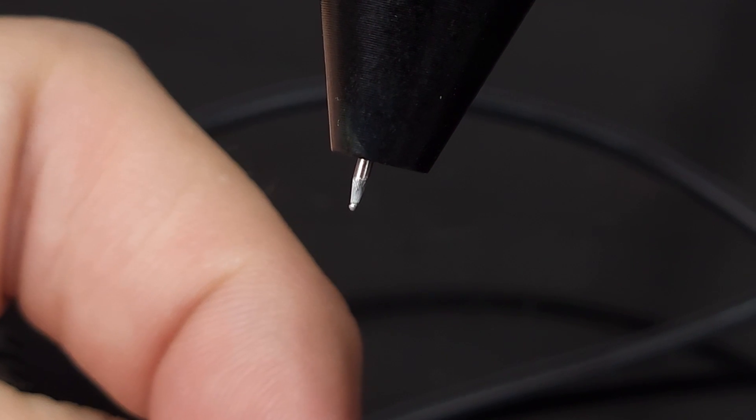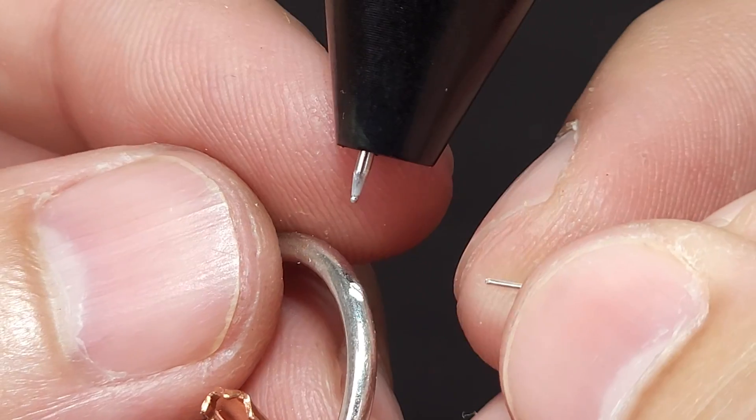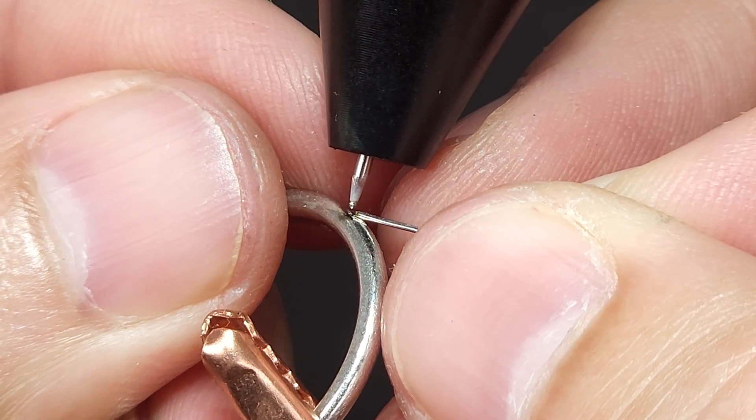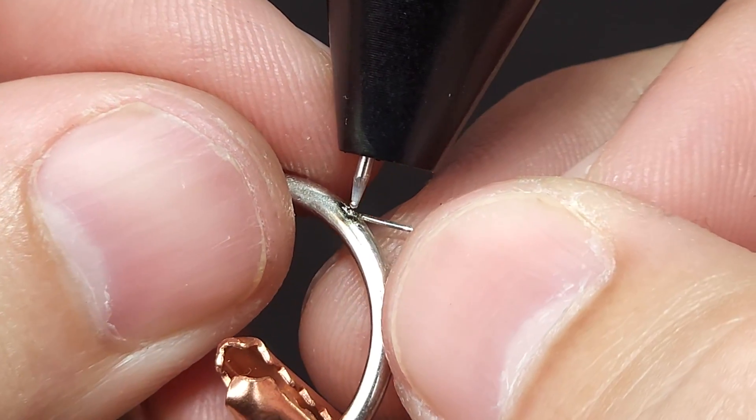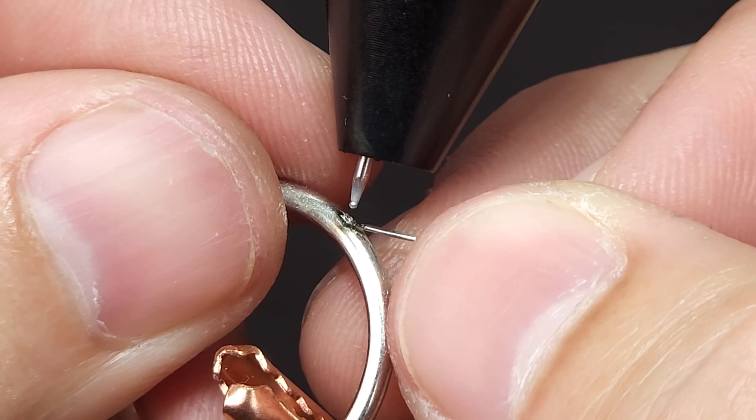Now let's say that the wire or the ring was a poor casting. So to simulate this, I'm going to put a little gouge there. We can grind that out. And I'm using 10 watt seconds with no agitation right now. So again, I'm going to do some welds. And as a reminder, you can see that the welds aren't performing as well as I would expect them to. And that's because our electrode has gotten dirty.